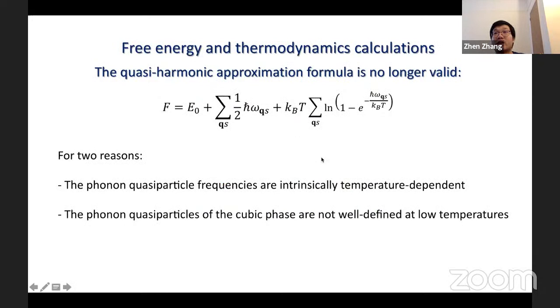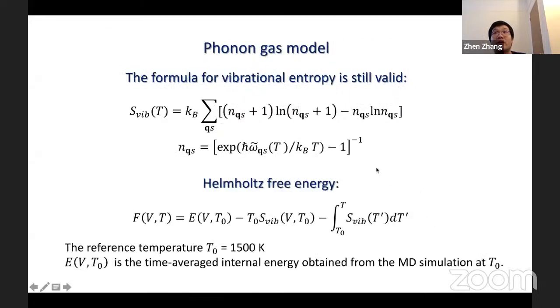To calculate free energy and thermodynamic properties of calcium perovskite, the quasi-harmonic approximation formula is no longer valid for 2 reasons. First, the phonon quasi-particle frequencies are intrinsically temperature dependent, while quasi-harmonic approximation treats phonon frequencies as intrinsically temperature independent. Second, the phonon quasi-particles of the cubic phase are not well defined at low temperatures, so we cannot use the quasi-harmonic approximation formula. However, within the phonon gas model, the vibrational entropy formula is still valid. The temperature-dependent phonon spectra can be used to compute vibrational entropy, then Helmholtz free energy. The Helmholtz free energy can be calculated by the integration of the vibrational entropy.